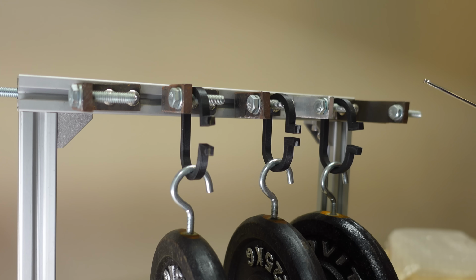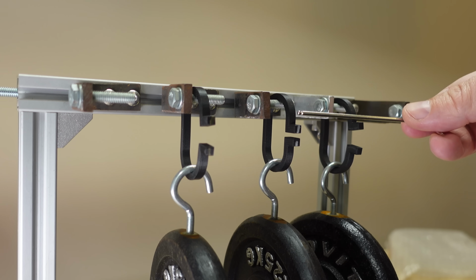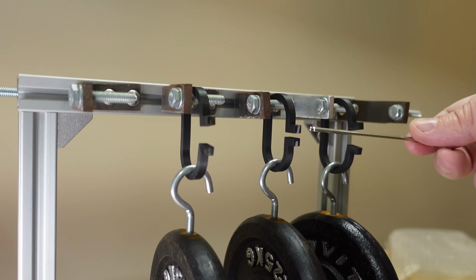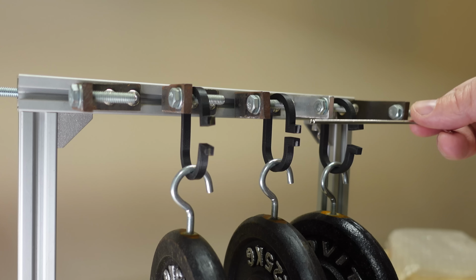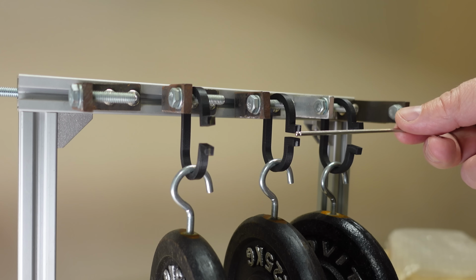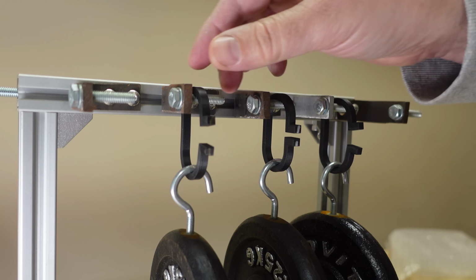1272. This is the last 5 days, I already measured them, and again I can see slightly more deformation on group 3 compared to group 1. And on this one reinforced with glass fiber, absolutely no additional deformation. There is some small inaccuracy in measuring because I cannot use the holder here, but basically no deformation on this one. Now let's remove the load.